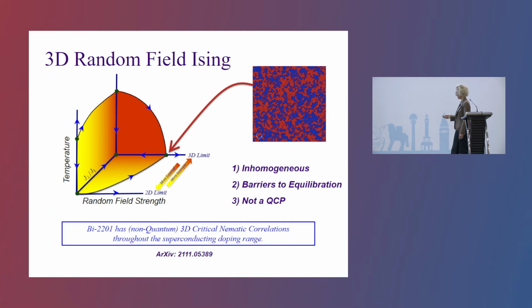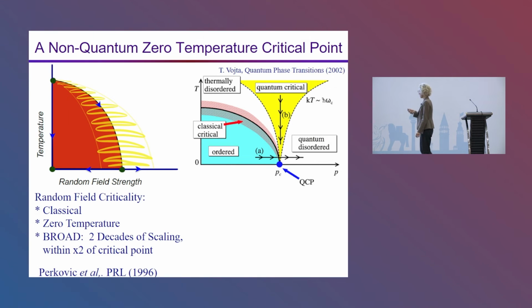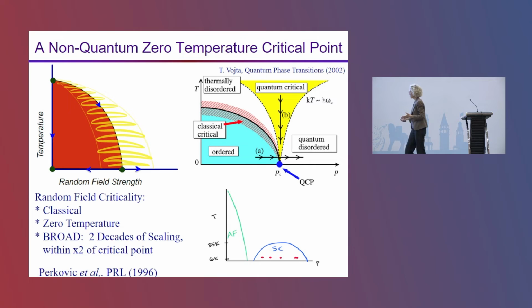But moreover, I want to emphasize that this is not a quantum critical point. So what does a quantum critical point look like? At a quantum critical point, as a function of some parameter, you're increasing quantum fluctuations, and the critical region is actually pretty narrow. It would be confined to the critical doping, and come up in a wedge at temperatures above that doping. It's a narrow range. Whereas what we're seeing here is that the data set coming out of Hoffman and Eric's group is critical throughout the doping range.